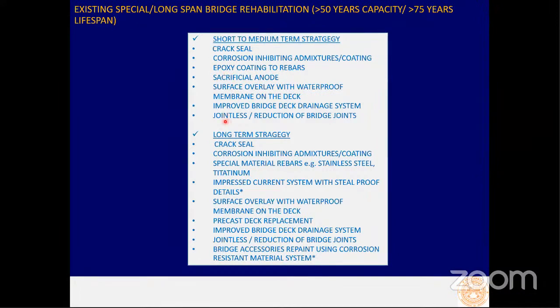However, if we have sufficient budget, we can invest in the long-term strategies, right, every 30 years, okay? We incorporate not only the crack sealing, we're going to do some kind of strengthening by using the special material rebar, right, stainless steel, titanium. We can incorporate the impressed current system with the steel-proof detail. For example, we protect the steel by embedding the impressed current system inside the concrete section.